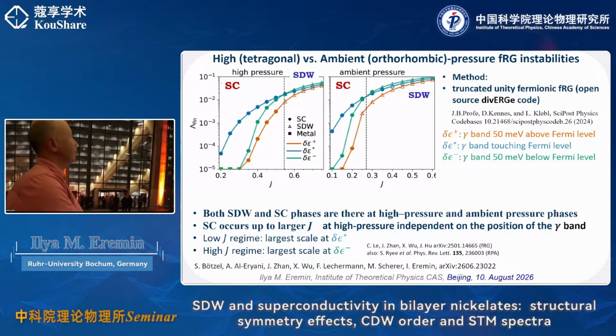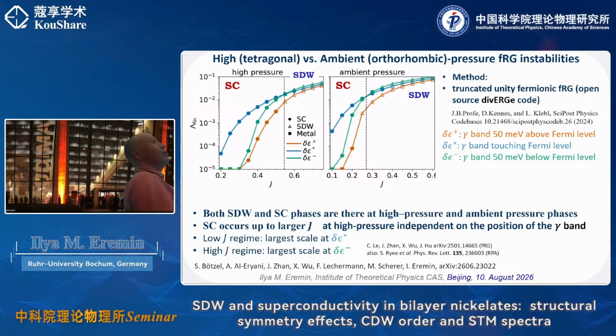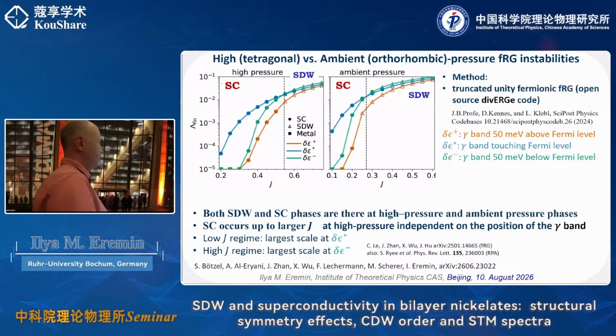Now, what is the difference between these 3 curves? The difference between these 3 curves is again the position of the gamma pocket, because since it still has been kind of ambiguous, we played with 3 different parameterizations. So with the gamma pocket being well above the Fermi level, it seems that it's not a good situation, neither for this spin density wave nor for superconductivity.